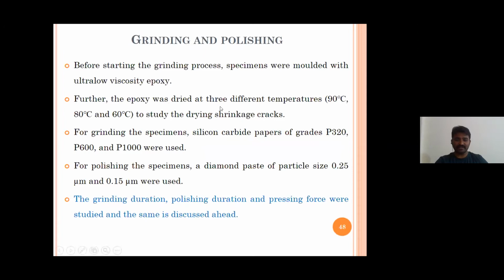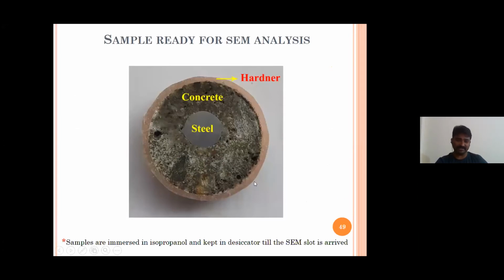Further, these ultra low viscosity epoxy samples were dried at 3 different temperatures. In the literature, it was mentioned that we have to use 90 degrees Celsius. But in our case, as I went with 90 degrees Celsius, there were some shrinkage cracks that we were observing at the interface. So to reduce those shrinkage cracks, we have gone for 80 degrees Celsius and 60 degrees Celsius also. For grinding the specimen, silicon carbide papers of grade P320, 600 and 1000 were used. For polishing the specimens, diamond paste of particle size 0.25 and 0.15 were used. Grinding duration and the grinding and polishing pressing force were also studied. So I'll come to those parts while I discuss the results and discussion.